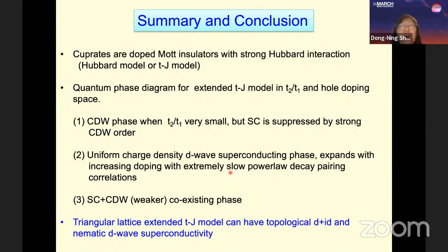So let me summarize my talk. We discussed some evidence from experiments that cuprates are related to doped Mott insulators with strong Hubbard interaction. This is the starting point for our numerical simulation. We showed the global quantum phase diagram for the extended TJ model in the T2 over T1 and the hole doping parameter space. We identified that when T2 over T1 is very small, we have a stripe phase where the superconductivity is suppressed by the strong CDW order.